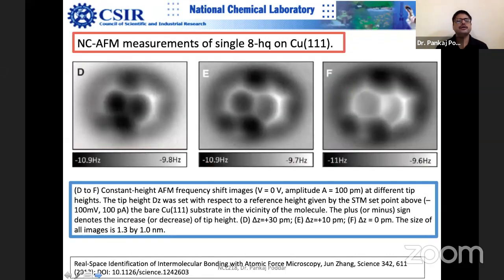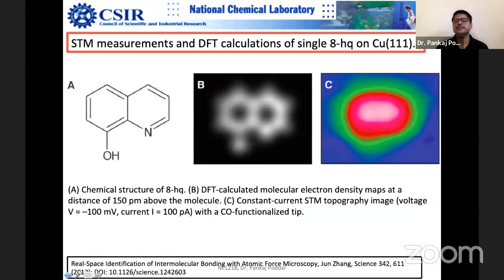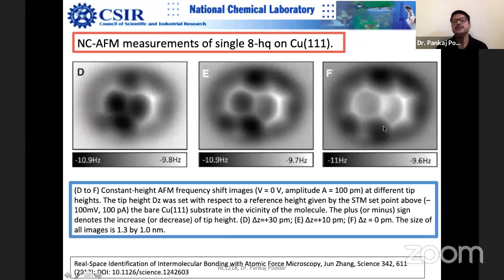But in force measurement, because you are not measuring the current, in a non-contact AFM, look at this beautifully, you can start seeing both the rings clearly. Amazing. This is the beauty actually; you can't even do this so nicely in electron microscopy. Probably advanced versions of electron microscopy, high resolution aberration corrected, you can see. But this is much simpler because there is no need for